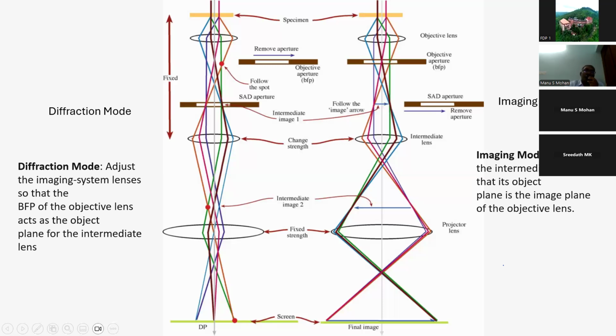So basically, imaging mode and diffraction mode, you can switch between with ease while operating a TEM, just by changing the strength of the intermediate lens, that is, adjusting the current through the intermediate lens. You can change the strength of the lenses, which will decide whether you want to focus a final image or a diffraction pattern.